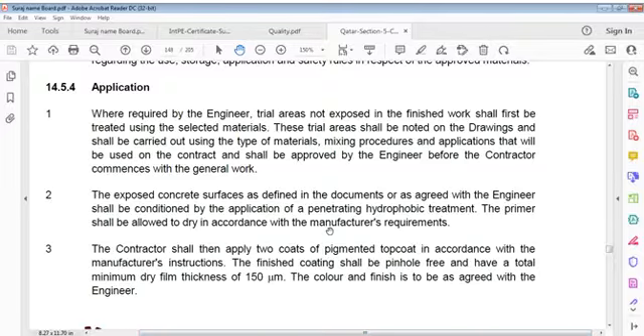So let's say exposed concrete surface defined in documents or as agreed with engineers shall be conditioned by application of penetrating hydrophobic treatment. Primer shall be allowed to dry in accordance with manufacturer's requirements. Contractor shall then apply 2 coats of pigmented top coat in accordance with manufacturer's instructions. Finished coating shall be pinhole free and have a total minimum dry film thickness of 150 microns.